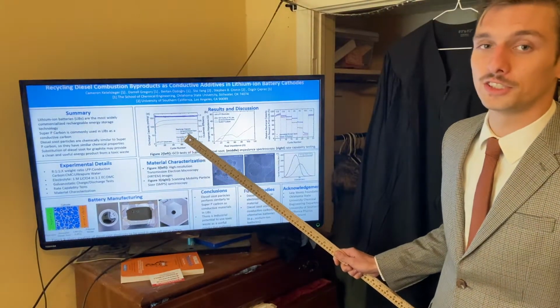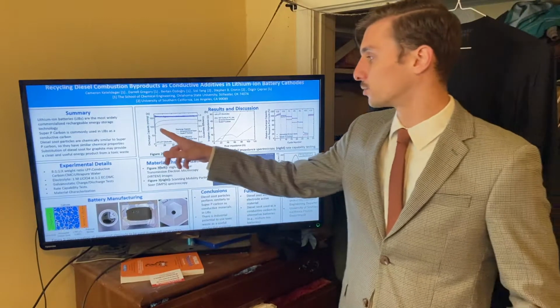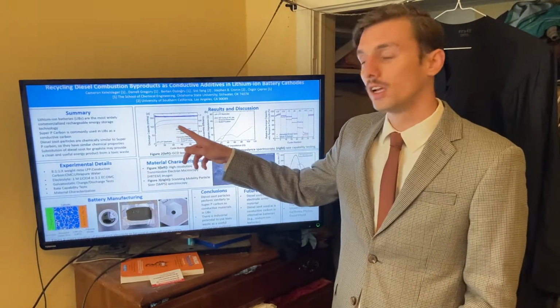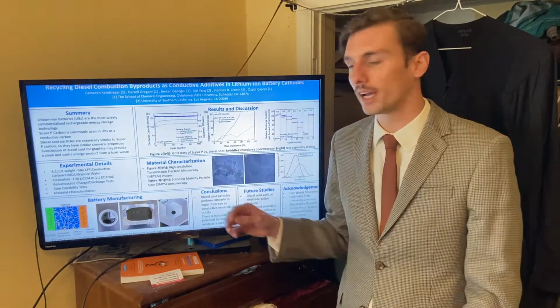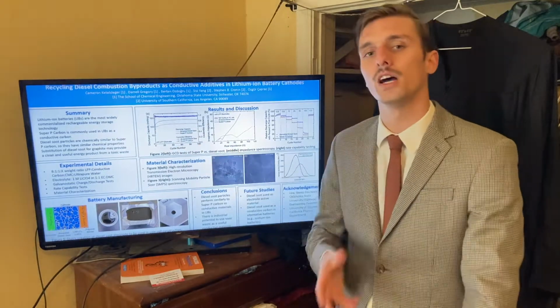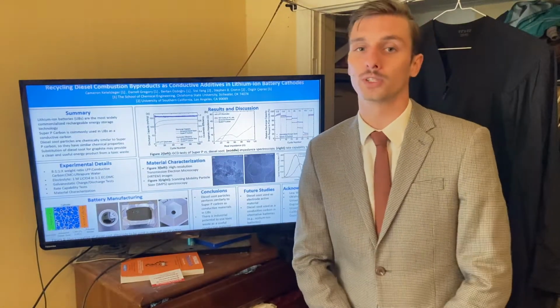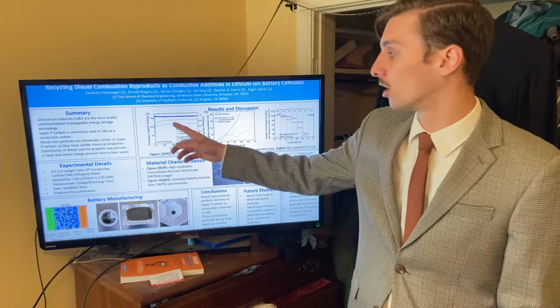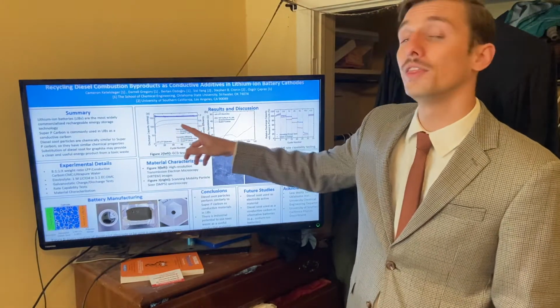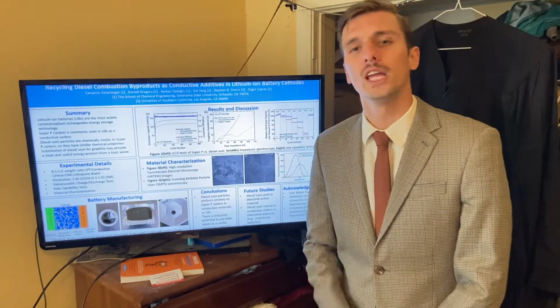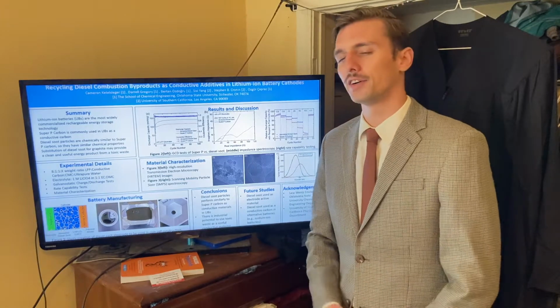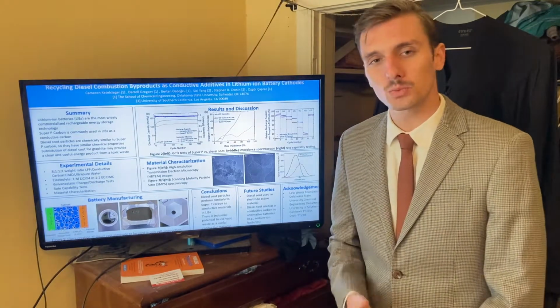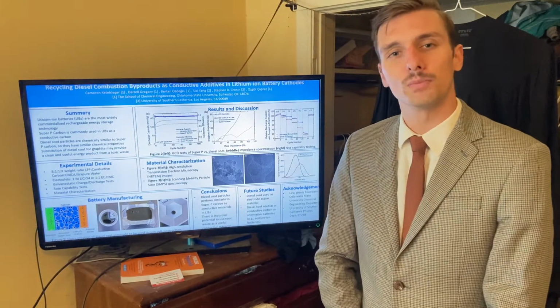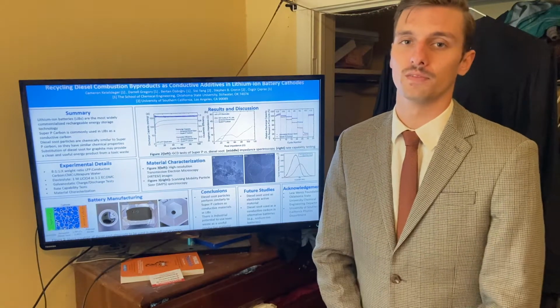Right here is our GCD curve. This red line right here is annealed diesel soot, which we found an average discharge capacity over 100 cycles to be 110 milliamp hours per gram. We found for Super P carbon, the industry standard, is 130 milliamp hours per gram. Even though these are slightly different, they're pretty close. So that's really what we want to see for a replacement material like annealed diesel soot.